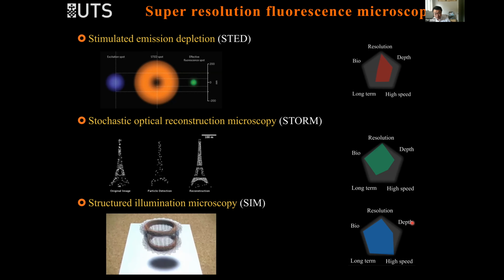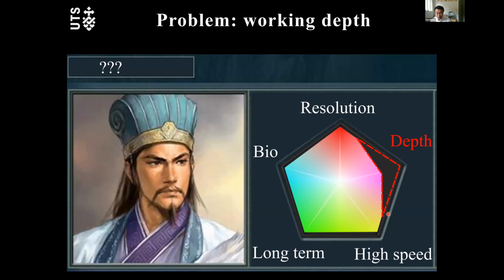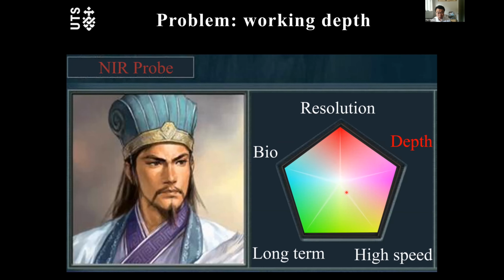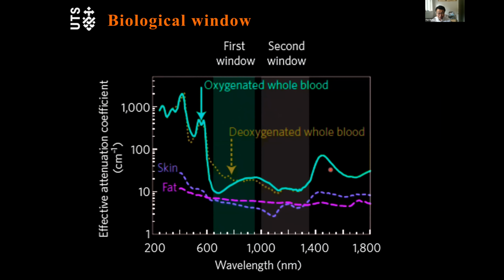So if you look at all the major technologies, they all have limited working depth. This is the current limitation for most of the technology. So what we want to do is use our near-infrared probe to solve this problem. Because if you have both the excitation beam and the emission beam in this first biological window, you can have longer penetration depths. And once this happens, you're supposed to have super-resolution with longer penetration depths.